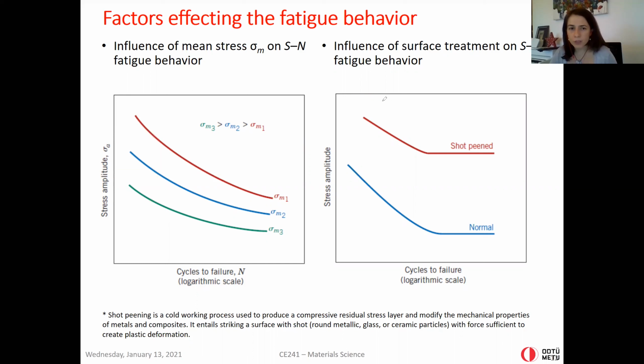The second curve actually shows two different surfaces, as surface is very critical on fatigue behavior. Cracks most of the time start from the surface. The red one is shot peened, and the blue one is a regular surface. Shot peening is a cold working process used to produce a compressive residual stress layer and modify the mechanical properties of metals and composites. It entails striking the surface with shot. Shot is basically round metallic, glass or ceramic particles with a force sufficient to create plastic deformation. So the surface becomes a little bit rougher. So as you see, when you improve the surface, you actually improve the fatigue performance significantly.